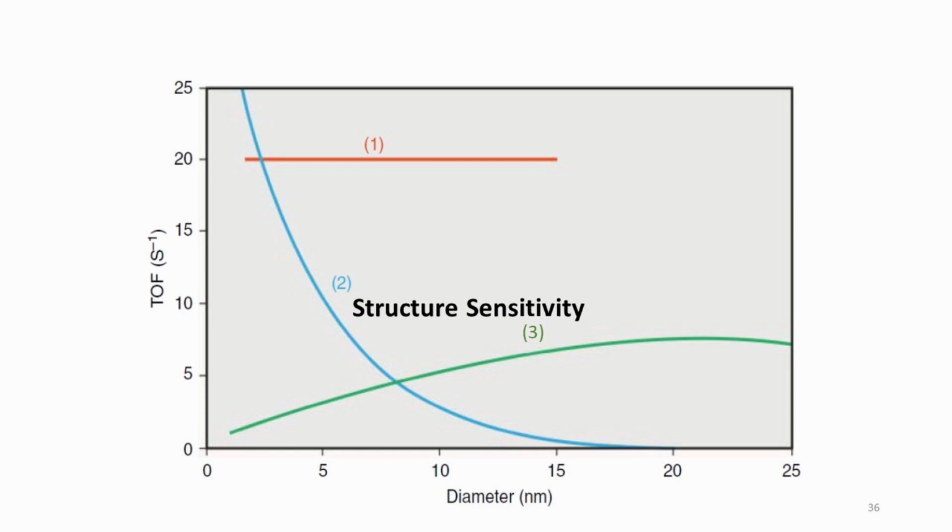The third type occurs in CO hydrogenation, in which the key reaction is a cleavage of the strong triple CO bond. It has been observed that the turnover rate increases with particle size, and sometimes it also shows a maximum at intermediate particle size.